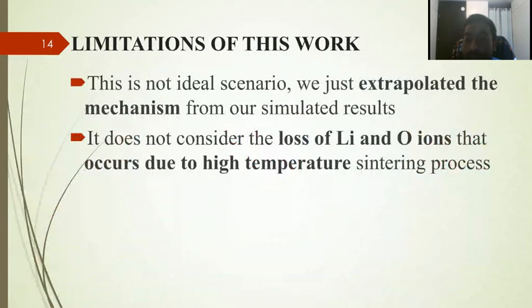So it is clear from here that the limitation of this project is this is not an ideal scenario. We just extrapolated the mechanism from our simulated results. And the consideration of lithium and oxygen loss due to high temperature has been disregarded because this is a simulation process. Next.